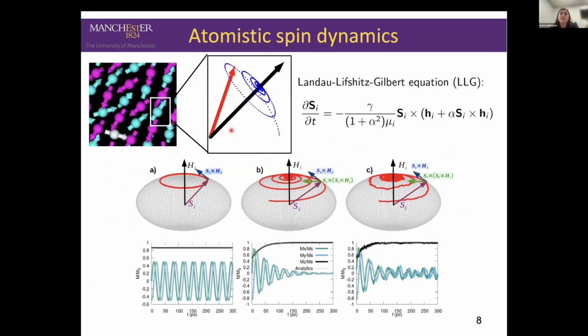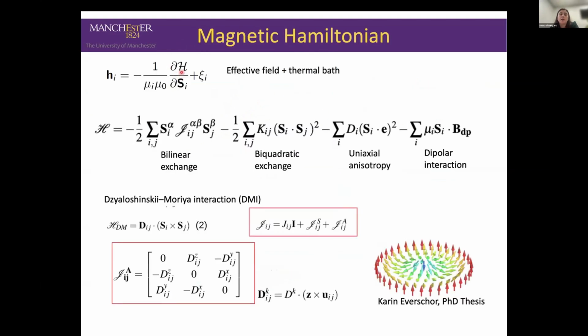So to describe in a bit more depth atomistic spin dynamics, what we do is assign to each atom in our magnetic material a spin, which is a classical entity, and we allow this to evolve according to the Landau-Lifshitz-Gilbert equation. So we'll have this precession and this damping term. So we numerically integrate the Landau-Lifshitz-Gilbert equation. In this equation, we have this effective field, which can be calculated based on the Hamiltonian of our system and can be augmented by a thermal field. So we can now perform finite temperature simulation by connecting it to a thermal field and Langevin dynamics.